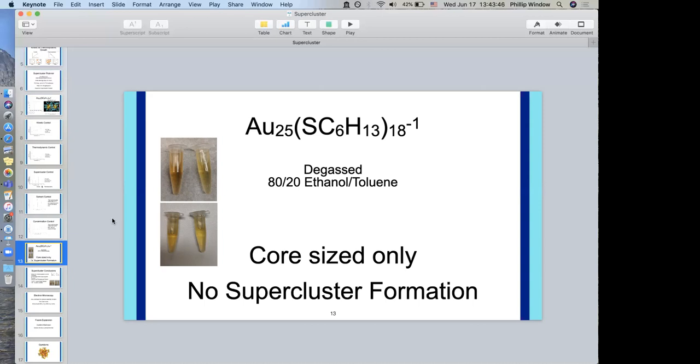You probably could change ligands from an alkane thiol to something else, maybe not an aromatic thiol, or a phenyl group on the end of your thiol, because those pi-to-pi interactions might be too strong. But something else that you might be able to do is more of a covalent attachment with a larger nanocluster. Yeah, that's really cool. As a spectroscopist, I can appreciate being able to access different size windows by changing the ratio of, like you said, counterion to the core. That is pretty cool.